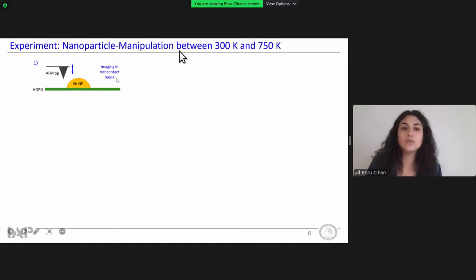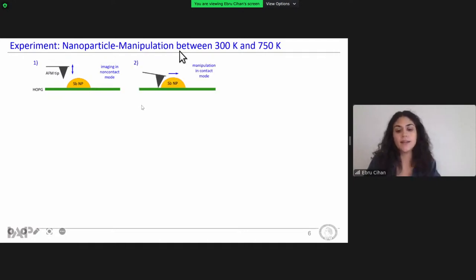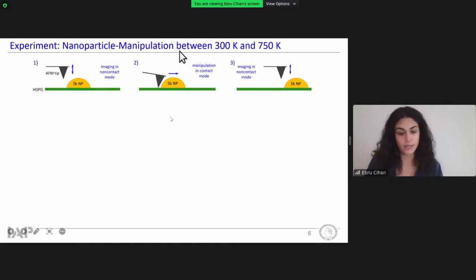To avoid scattering-induced movement of nanoparticles, the sample was first imaged in non-contact mode, and then a nanoparticle suitable for manipulation was chosen. Then the AFM tip was placed directly next to the nanoparticle, and the system was switched to contact mode, and then nanoparticle manipulation was performed laterally. After the manipulation, particle displacement was confirmed again in non-contact mode.